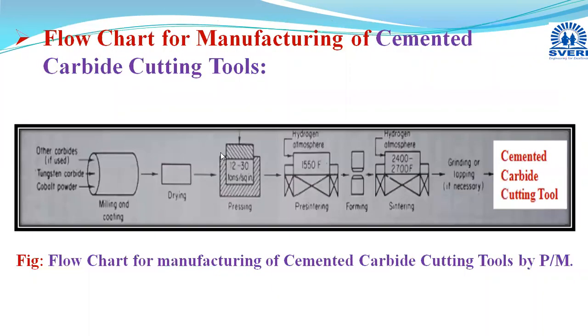Now the same I have highlighted here with the help of the flow chart. This is the flow chart for manufacturing of cemented carbide cutting tools by powder metallurgy technique. Tungsten carbide or other carbide particles, molybdenum carbide particles are manufactured. Cobalt powder particles are manufactured by a reduction method, and they are given to the mixing process. In some books it is mentioned as milling. Here we are adding some lubricants like paraffin wax in petrol, camphor in ether, or glycerin in alcohol. Lubricants are added to provide sufficient lubrication. Here pressing is done at 35 to 45 kg per mm square pressure.